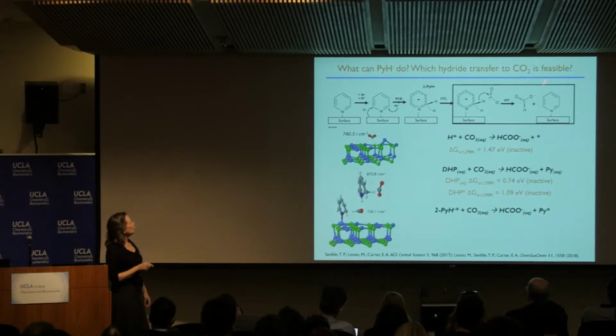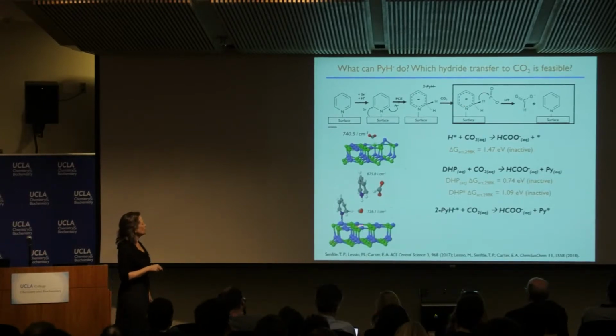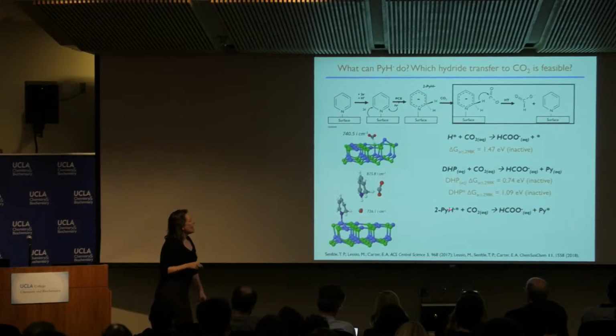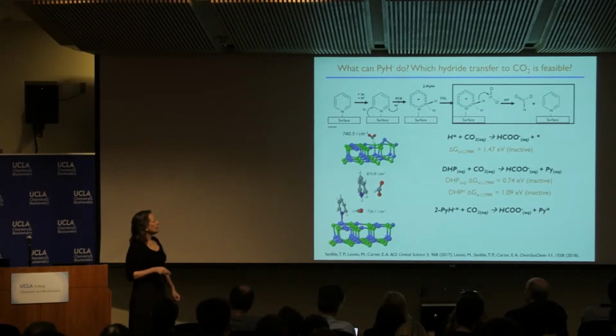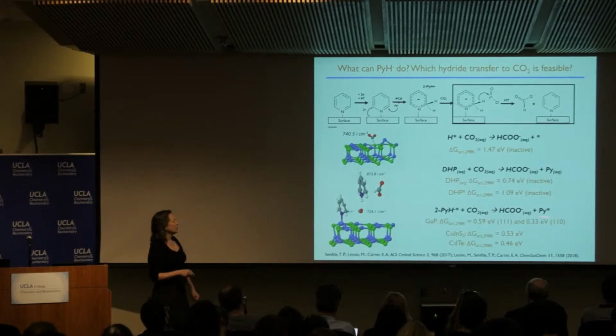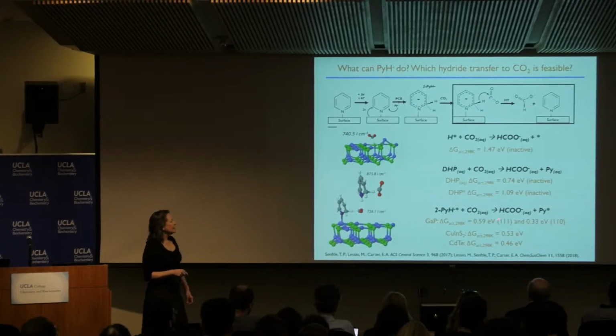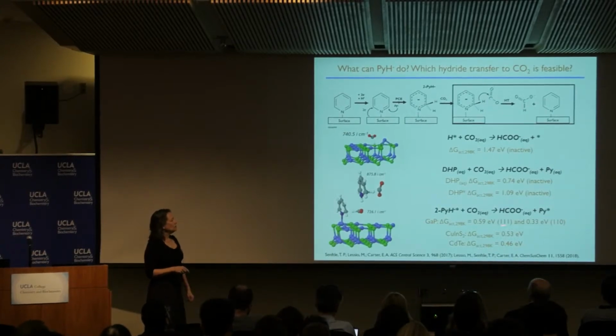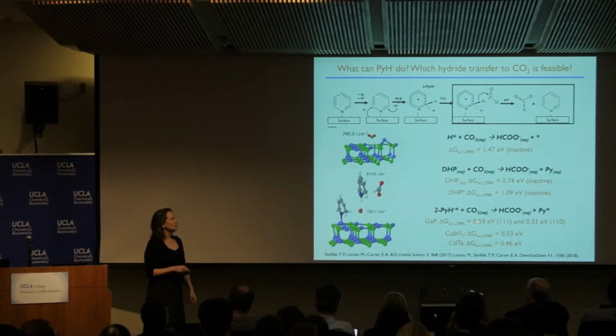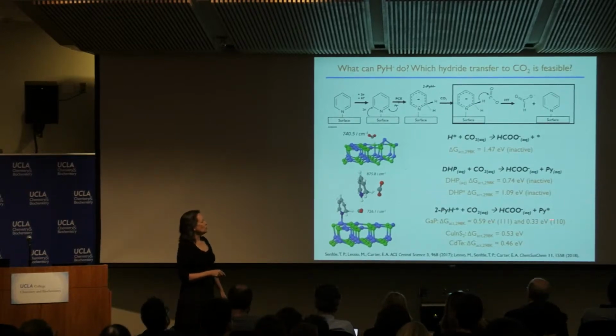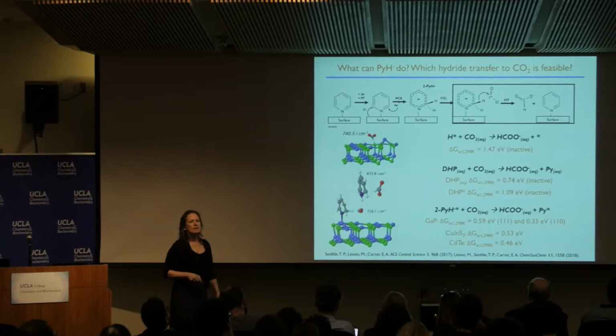On the other hand, if you look at this 2-pyridinide here, here's a picture of it, and you ask, can it make formate, and what are the barriers? We looked at all 3 surfaces, and all the barriers are essentially within reason. In fact, what's interesting about this result is that we predicted that on the 111 surface, the barrier might be a little bit high, and if you go to this 110 surface, it drops in half.